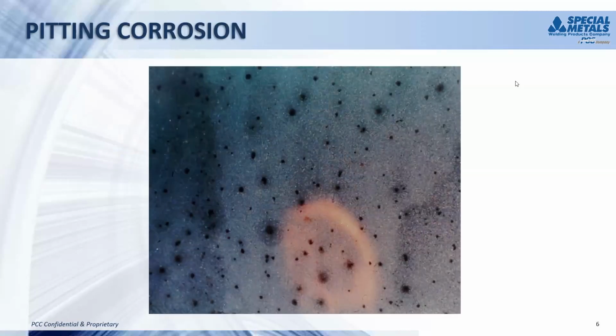The next slide shows some of the type of corrosion we see. Typically, the corrosive mechanisms encountered in FGD systems are of the localized type. Pitting corrosion, as we see here, can be a very dangerous type of corrosion in that while the general corrosion rate of the material may be very low, the pit, once initiated, can bore its way all the way through the complete section, causing a leak very quickly. And the next slide,